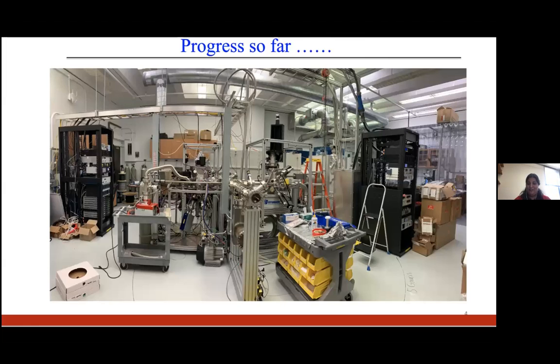And so far we have made good progress in the last 2 years. We have a fully operational MBE chamber, and we are currently growing epitaxial thin films of sodium bismuth, which is a 3D Dirac semimetal. And the in-situ magneto-transport chamber is also coming along, and we are hoping in the next 10 days we'll be able to test it and do our first device measurements in there.